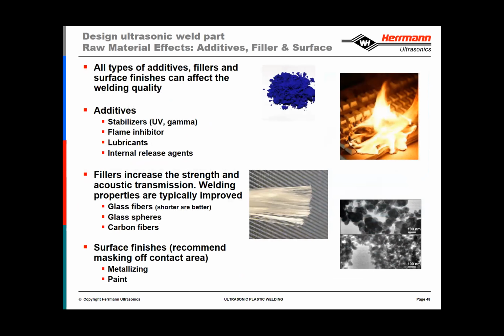And then finally, surface finishes. If you have a chrome plated or metallized part, or if you have a painted part, we see this often in automotive applications. That coating or that surface finish, the metallizing or the paint, becomes a contaminant or a weld inhibitor. So for those areas that you intend to weld to a metallized or a painted surface, either they should be masked off prior to the surface finish being applied, or the surface finish may have to be removed prior to welding. Depending on the thickness of that surface finish, we may be able to break through that surface finish, but best practice would be to eliminate it in the welding area or remove it as needed.